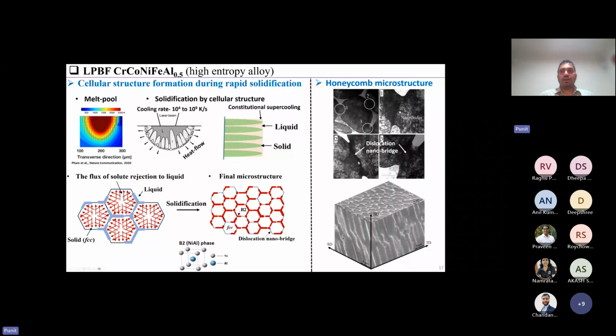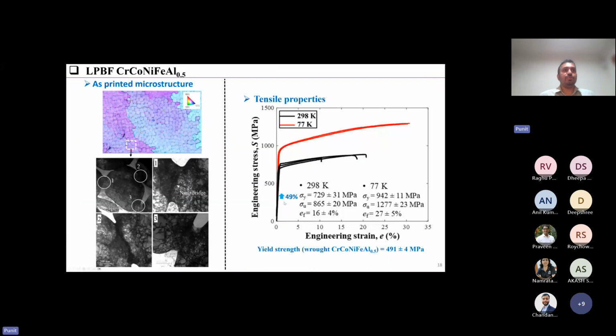And essentially this microstructure that we formed through LPBF processing of this composition, we call it honeycomb microstructure, which, if you look at this pseudo 3D microstructure diagram, you can see it resembles a honeycomb. So we went ahead and did some tensile tests on this material. And when we do the tensile test, we see the yield strength at room temperature increases by 49% compared to the wrought counterpart of this alloy.